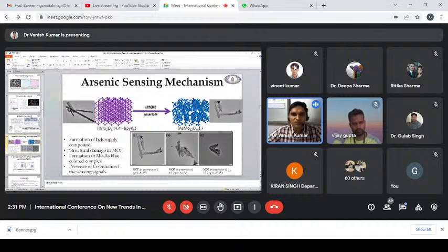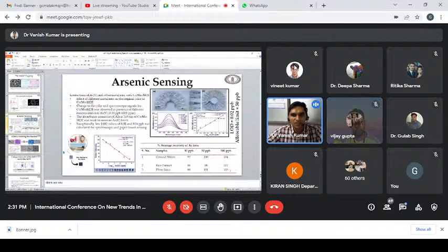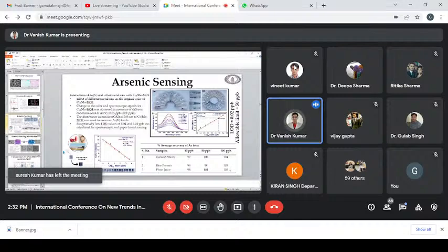Due to degradation of the structure of the MOF, these peaks started going down. As we increase the concentration of arsenic, the structure of the MOF was degraded, and with increasing concentration of arsenic, more structure of the MOF was degraded, and there is a larger dip in this peak. So we further characterized the arsenic-treated MOF with TEM to check whether there is degradation or not.